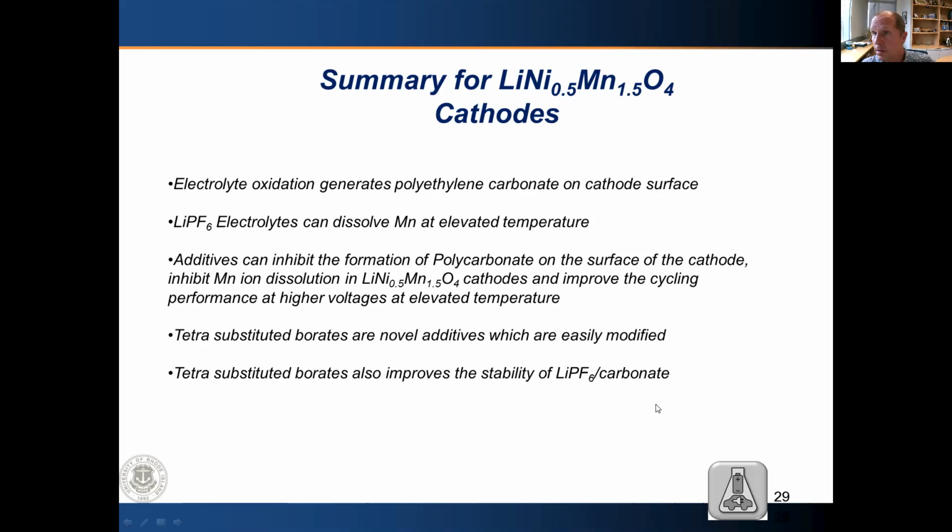At the beginning of this talk, I mentioned that LiPF6 has thermal stability issues, where if you heat it in the presence of carbonate electrolytes, these electrolytes can decompose. In addition to being oxidized on the surface of the cathode, these tetra-substituted borate additives also inhibit the thermal decomposition of the LiPF6 based electrolytes in the bulk solution. So this is an additional benefit of the additive.